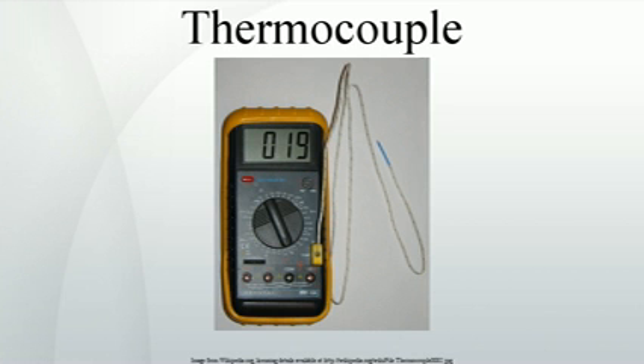The nicrosil and nisil thermocouple alloys show greatly enhanced thermoelectric stability relative to the other standard base metal thermocouple alloys, because their composition substantially reduces the thermoelectric instabilities described above. This is achieved primarily by increasing component solute concentrations, chromium and silicon, in a base of nickel above those required to cause a transition from internal to external modes of oxidation, and by selecting solutes, silicon and magnesium, that preferentially oxidize to form a diffusion barrier, and hence oxidation-inhibiting films.